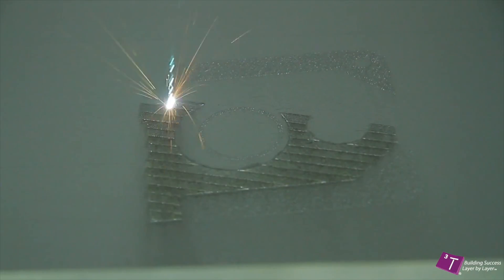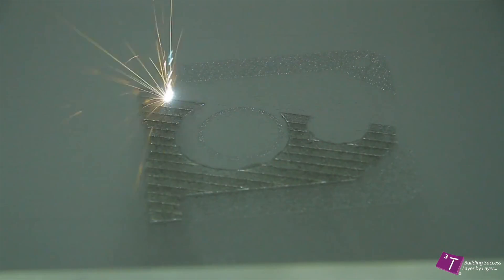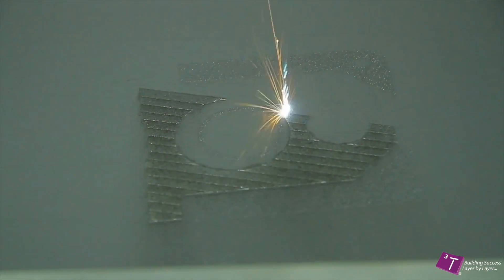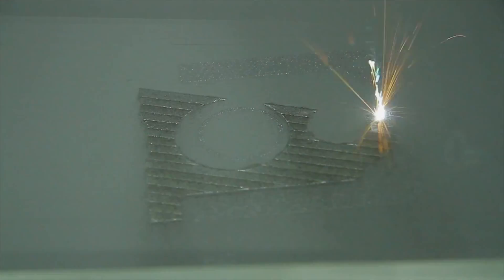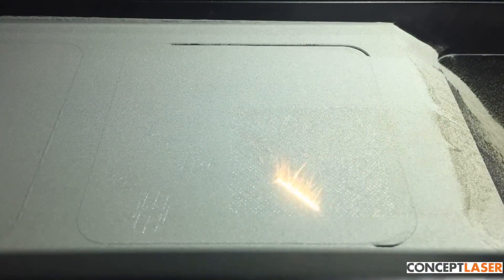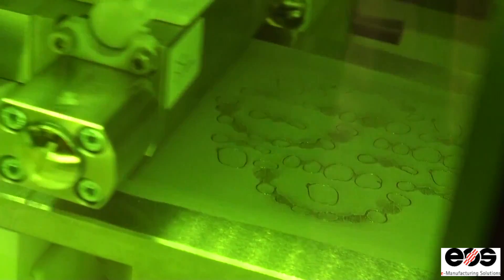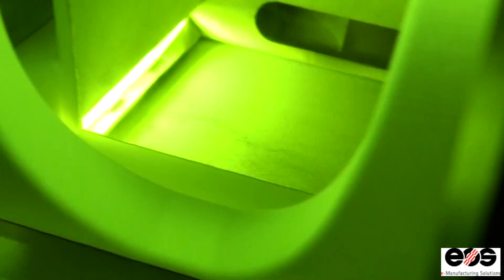If the focused spot location is before or behind the build plane, or the distribution of the laser power is not optimized, inadequate melting of the metal powder will result. Any or all of these conditions will leave you with a part that is not metallurgically correct and structurally compromised to some degree.